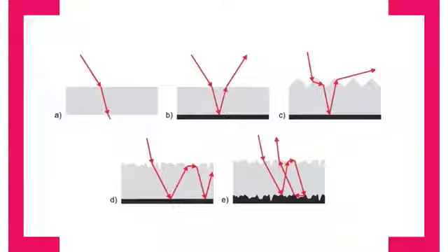The reason being that this kind of pyramidal structure is very easy to make in silicon. You just stick a certain crystalline structure of silicon in a bath, in a chemical liquid. And very quickly you create the structure, because certain crystalline directions are dissolved faster than other directions. So it creates the structure very easily. You can, of course, make it more random and higher spatial frequency, so smaller features. So it allows you to get more angles out, scatter light more. Okay. And of course, you can do it on both surfaces.